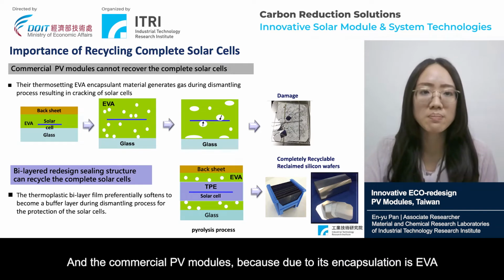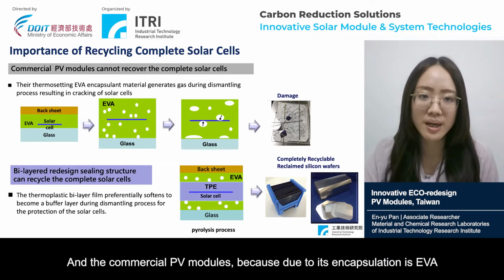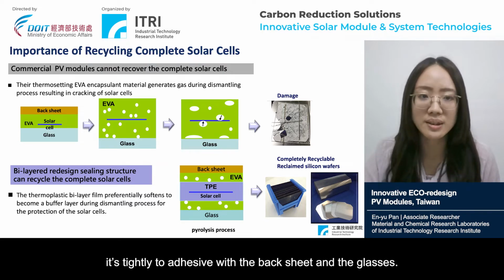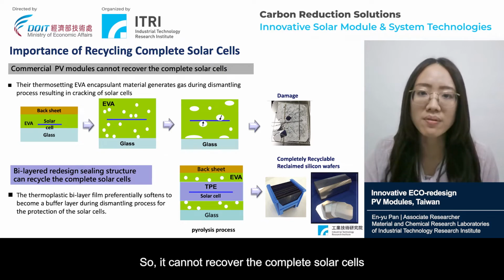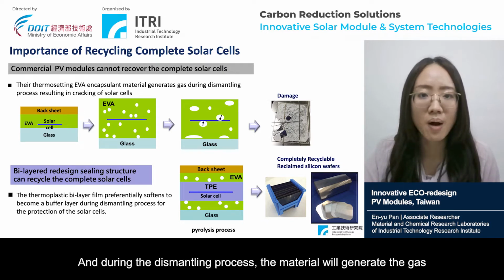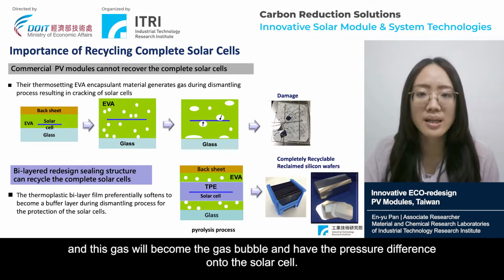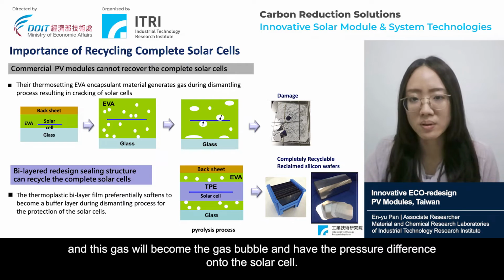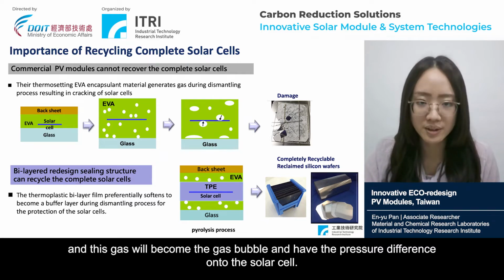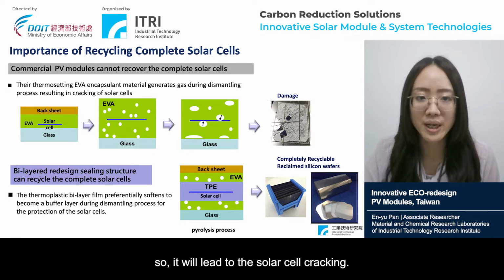In commercial PV modules, the EVA encapsulation adheres tightly to the backsheet and the glass, so it cannot recover the complete solar cells. During the dismantling process, the materials generate gas, and this gas becomes gas bubbles and creates a pressure difference onto the solar cell. So it leads to solar cell cracking.